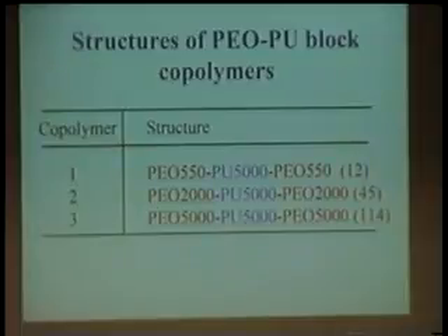So here are three of these copolymers where I'll show you data on today. You'll see them referred to as 1, 2, and 3, and the structures are very similar. They all have the same middle block of molecular weight about 5,000, and different molecular weight end blocks, 550, 2,000, and 5,000, and these correspond to, this is the number of ethylene oxide units, 12, 45, and 114. So these are oligomeric, I would say, rather than high polymer PEO segments.